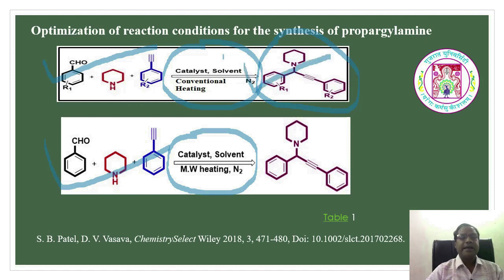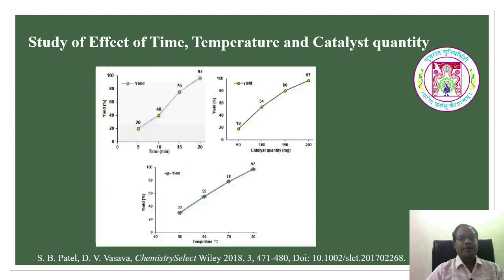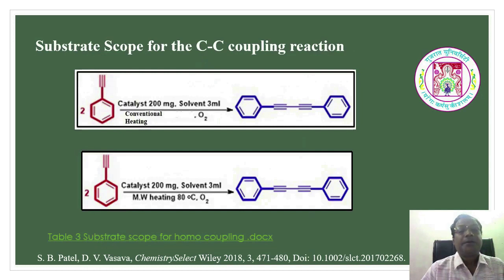Not only that, the conventional method required 24 hours to complete the reaction with 84% yield, whereas here we have reported a 97% yield of the propargylamine within 20 minutes. So here there is a study given. The yield is obtained at around 97% at 20 minutes, whereas it required only 200 milligrams of catalyst. And also this 97% yield is reported at 80 degrees Celsius temperature.